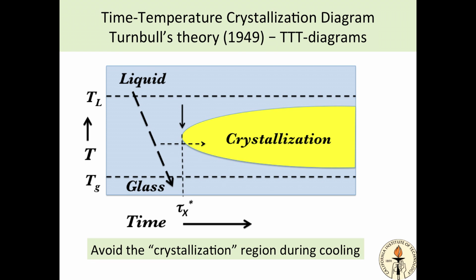And there's some temperature down here in the liquid cooled below the melting point, but still above the glass transition, where that crystallization rate is maximum. And we have to cool fast enough so we don't hit this on the way down. That's schematically what we have to do. If we can do that, we make a glass.